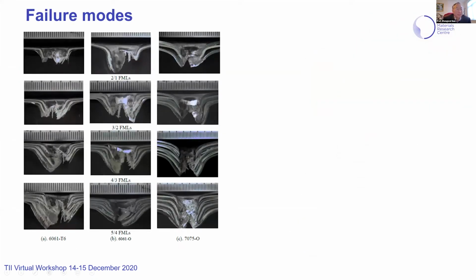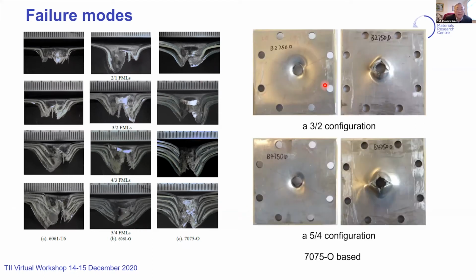Now I am going to talk about some test results. These are different fiber metal laminates, 2.1, 3.2, 4.3, and 5.4, with three different aluminium alloys. We can say they have similar failure modes under projectile impact, even with different stacking sequences. The primary feature is delamination between the metal layers and the composite layers, and of course we have cracks. This shows the front face and back face of the 3.2 and 5.4 configurations.